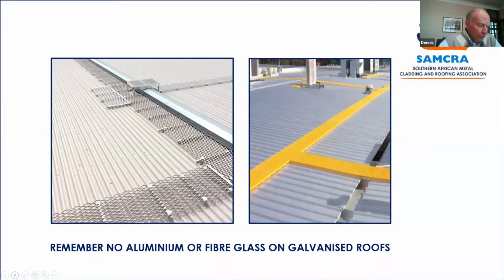Another material that you can use for it is woven wire mesh with apertures up to around 20-30 millimeter diameter, and that mesh is rolled, or should I say woven, from 1.6 millimeter diameter galvanized wire. Now again, anything that is pre-galvanized has a coating at best of Z275, which would amount to around 19 microns of coating. By comparison, a hot dipped galvanized surface has between 60 and 80 microns. So it gives you some idea of how thin that coating is, and there your expected life in a moderately corrosive environment would be 10-12 years before it started to rust.